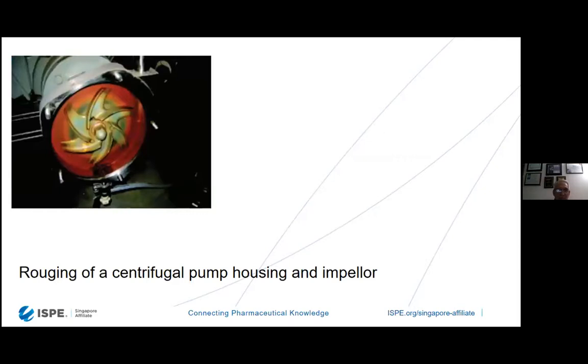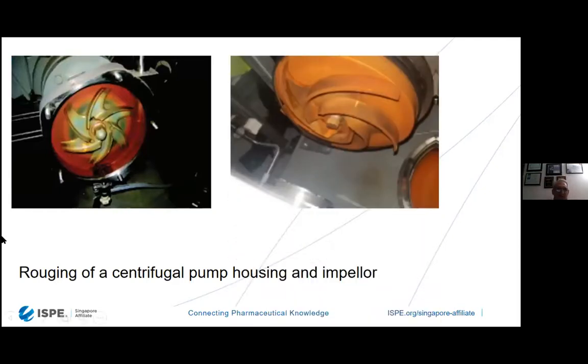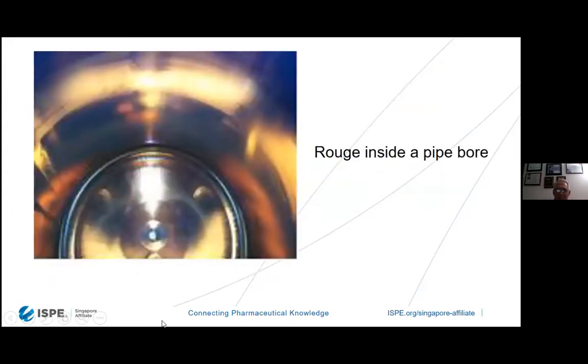as you'll see. This is two pump impellers from two different sites. You can see one over here, the pump impeller is actually a little bit better, and there's a lot of rouging outside of the pump impeller on the housing where it's sitting. On the other one, you can see that the rouge is on the pump impeller and on the housing and on the casing around that particular unit. Both of these rouges, if they flake off, will formulate those particulates we talked about. The rouge on here is primarily hematite and is class 2 rouge, but the particulates which could be taking off it would be class 1. This is inside a pipe bore, that color that we talked about before.